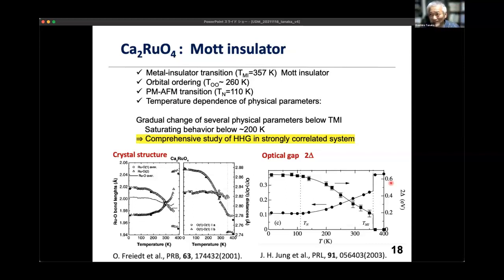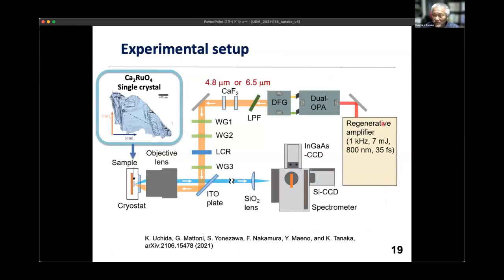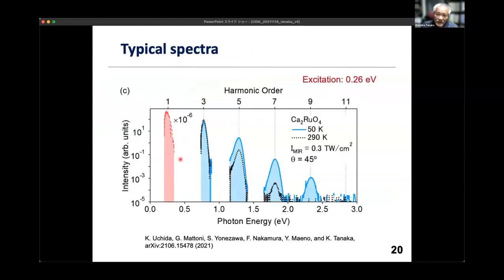Now we focus on this feature. Using this system, we measured high harmonic generation using the conventional titanium sapphire regenerative amplifier system, and using a dual OPA system, we obtained mid-infrared. We shined it on the sample, cooled in the cryostat, and using a reflective objective lens, we obtained high harmonics, in reflection geometry. Then we obtain these very nice high harmonics from this system.